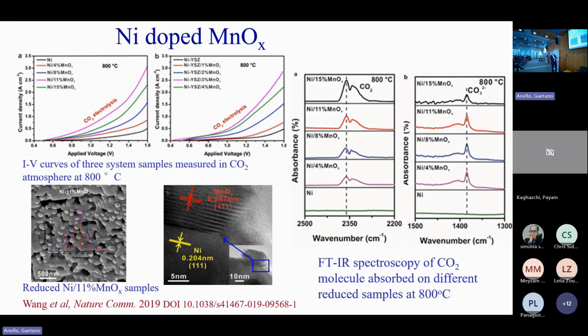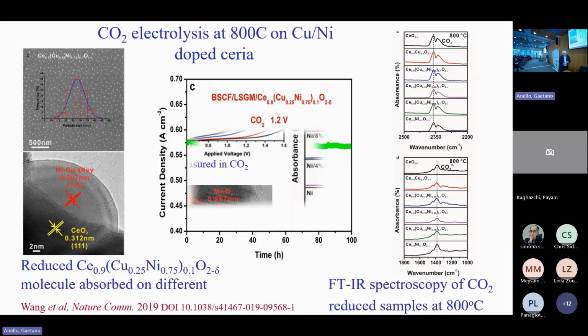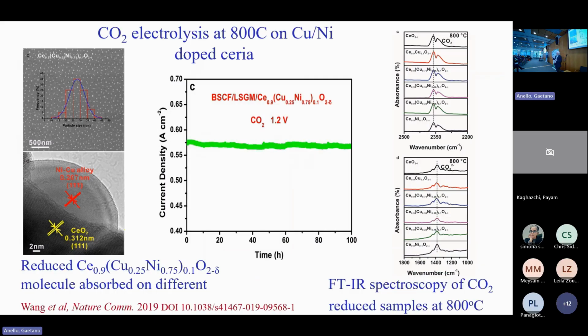Having manganese and nickel really works. And you find that manganese and manganese oxygen vacancies enhance the CO2 absorption. So having manganese in the structure improves the CO2 conversion. So manganese and exsolution are important. Another magic ingredient for CO2 is cerium. So cerium oxide and manganese are two particularly good systems. So this is cerium oxide that's got nickel copper inside. It's exsolved, and again you find the enhancement in the conversion with this cerium system.